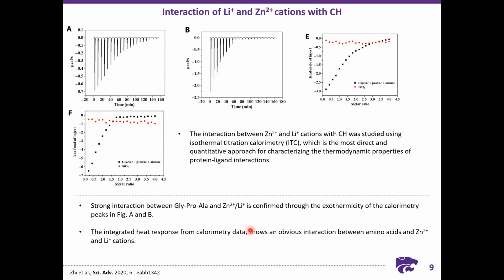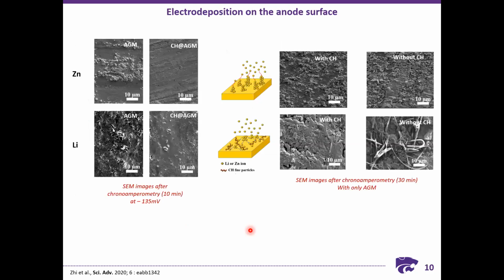So this tells us that there is interaction between the metal cations and the peptides. So the next step, they did SEM images after doing the chronoamperometry. They just deposit lithium for around 10 minutes at a negative 135 millivolt. So a continuous electrode deposition of lithium with and without the interlayers, and they took the SEM images after that.